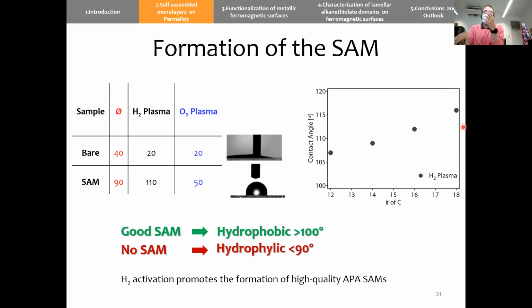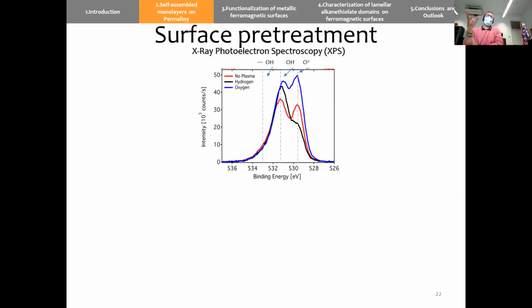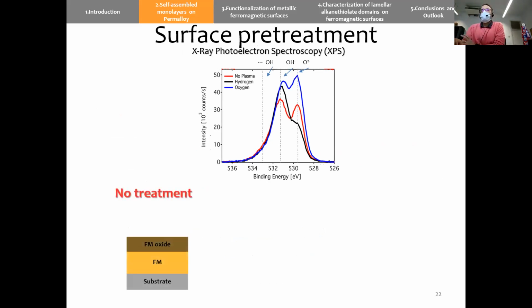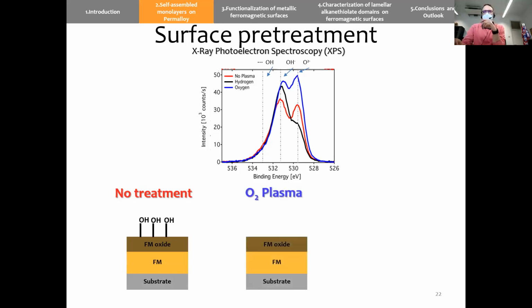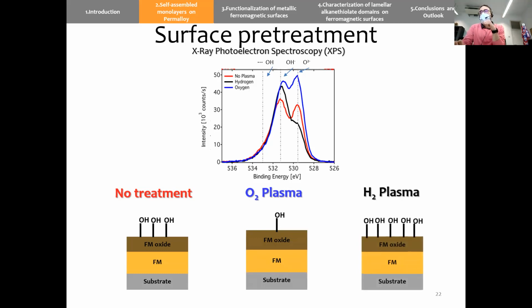In order to study why this effect was due to the hydrogen plasma, we performed XPS to observe how the oxygen peak changes when we do these kinds of treatments. With no treatment at all, we know that the bare material is oxide with also some OH. With the oxygen plasma, we increase the thickness of the oxide, but we reduce the OH density, while with the hydrogen plasma, we increase the OH density. And so this induces self-condensation when exposed to the phosphonic acids.